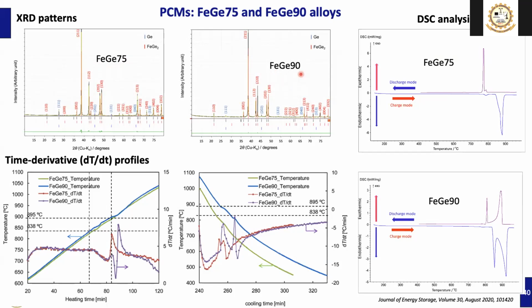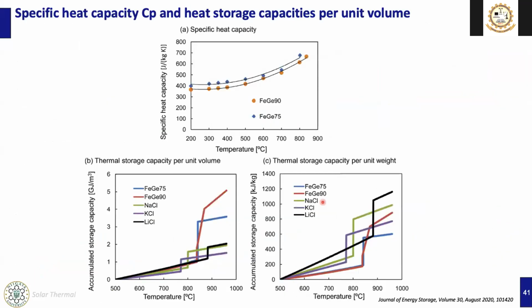And here you can see the accumulated storage capacity of iron germanium alloy is much higher than other salt materials like sodium chloride and lithium chloride. So as you can see, these materials give a very good accumulated storage capacity per unit volume. In this graph, you can see the accumulated storage capacity per unit weight. But the unit volume is very important for comparing different materials.